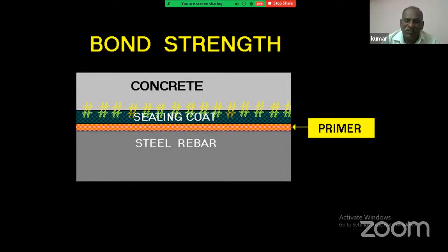What is the bond strength mechanism in this coating system? This is your steel rebar. You are applying a primer. The primer has a pi bond effect. So what happened? The primer bonds with the steel, which is Fe, and creates a film, having a higher adhesion. And the sealing coat of the same polymer is used. There is no difference between the adhesion on the interface of the primer and the sealing coat.